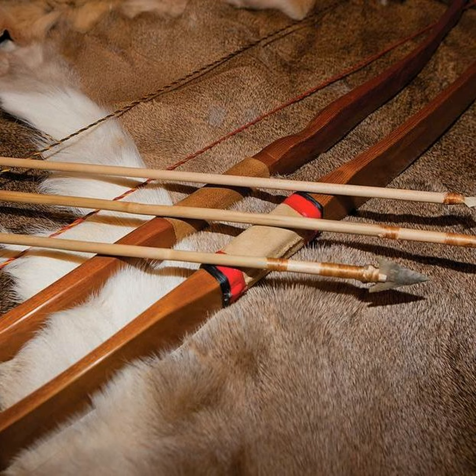So you've got a very balanced wood in the form of Osage orange. It's going to have a high bending strength with a high amount of stiffness. You look at balsam and you think, 1.4 million pounds per square inch is pretty high. Again, don't look at the numbers too much, but if you look at that ratio of 1-6, it's pretty stiff, but it's 6 times less bendable. That's bad. So that means it may be stiff, but when you try to bend it, it's going to snap relatively quickly. Balsam fir would be a terrible species for making a bow and arrow. Not a good idea at all.